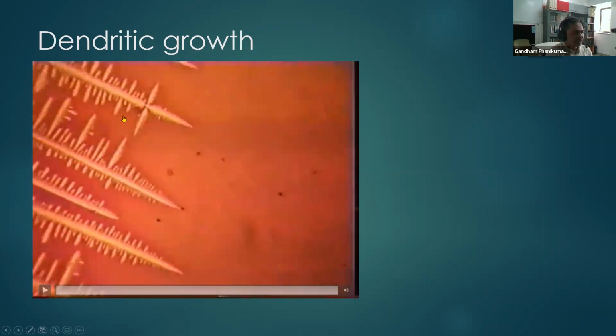Now, what is it that is in between the trees? It is basically the liquid which is yet to finish solidification, and that is enriched with solute. In the case of superalloys, it will be enriched with aluminum, titanium or niobium elements. Therefore, they lead to segregation patterns, which if you etch, you can make out these dendritic appearances. So one can etch and look at the microstructures to see these patterns.